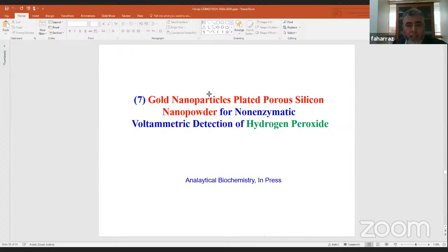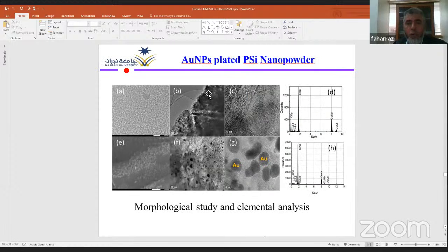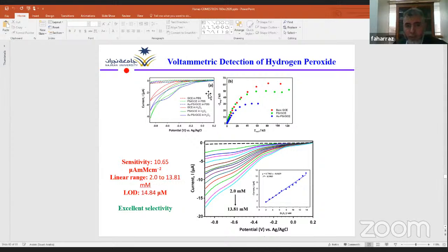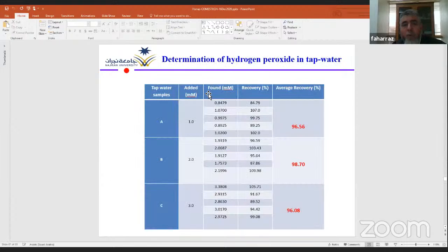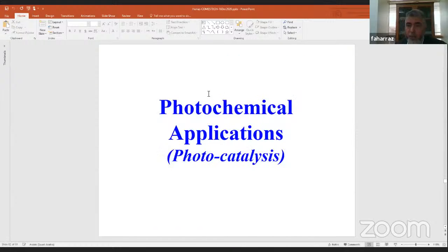And still very fast, an example of gold nanoparticles decorated porous silicon nanopowder for detection of hydrogen peroxide. This work was recently published in Analytical Biochemistry. And this is just to confirm the morphology of our hybrid structure of gold nanoparticles coated porous silicon nanopowder. And this is the voltammetric detection of hydrogen peroxide with a very nice sensitivity, linear range, limit of detection, and excellent selectivity. We also validated our sensor performance during the determination of hydrogen peroxide in tap water with promising and acceptable analytical results. This is the first part concerning sensor technology and the application of nanomaterials in sensor technology.